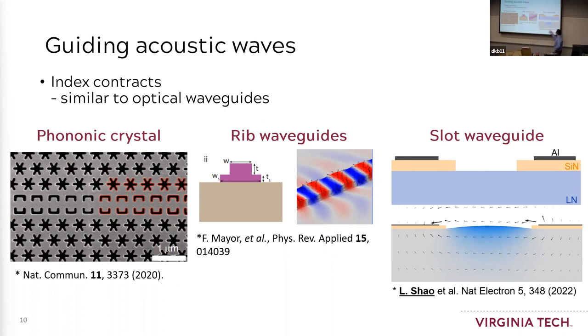There are several advantages. This waveguide does not explore the edges and boundaries, so it does not suffer from all the roughness due to the nanofabrication. The other thing is that by this way, the mode is mainly confined in the lithium niobate. So if you want to take advantage of the lithium niobate material properties, you want the acoustic mode to be confined in the material you want to utilize.